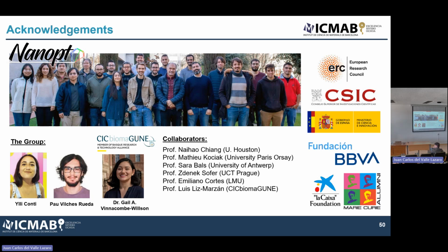Practically doing it with a soft ligand, since they are assembled, it's not that easy to say, okay, instead of using a PEG 2000, I use a PEG 800. Not as easy. So what we were trying to do is to use an inorganic shell, so silica on top, but it's easier said than done. Basically, we can make the spheres, we can make the silica shell, but it cannot be too big. There's always the eternal problem of growing a 20 nanometer silica shell. It's not easy. We managed to get something like a 50 nanometer, 30 nanometer silica shell, but then assembling them is